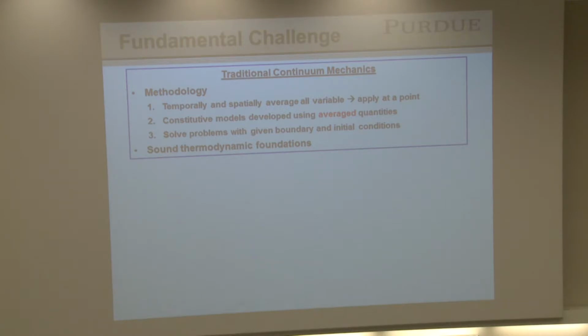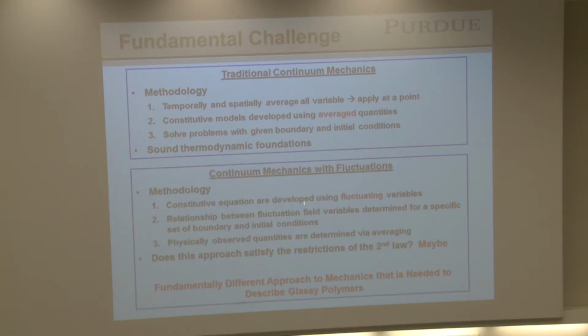And then once you have done the spatial average, you formulate a relationship called the constitutive model between these average quantities. And then finally, at that point, you solve problems with given boundary and initial conditions. This approach has a sound thermodynamic foundation, and it works well for most materials except when you get to the glass. What we've done is we are now looking at continuum mechanics with fluctuations. And so we are doing absolute violence to what you learn in the first page of any transport course. The methodology says the constitutive equations are developed using fluctuating variables.